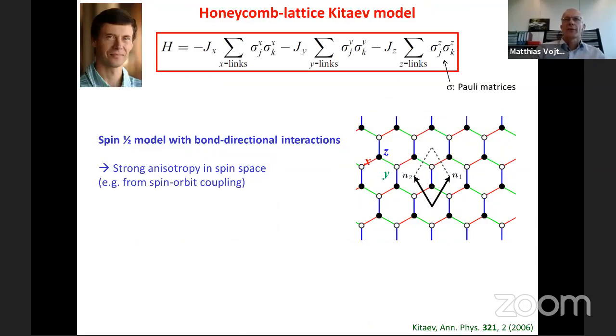I want to mention one other interesting field of work in the context of spin liquid, which has been pioneered by Alexei Kitaev in a by now famous paper in 2006. Kitaev proposed this interesting spin model here, which lives on a honeycomb lattice, which is by now known as the Kitaev model. This features anisotropic interactions. So there are three types of Ising interactions where the X, Y, and Z components interact on the red, green, and blue bonds of this lattice. So that's a model which corresponds to a strong anisotropy in spin space, which must arise from strong spin orbit coupling. And the special thing of this model is that it can be solved exactly.